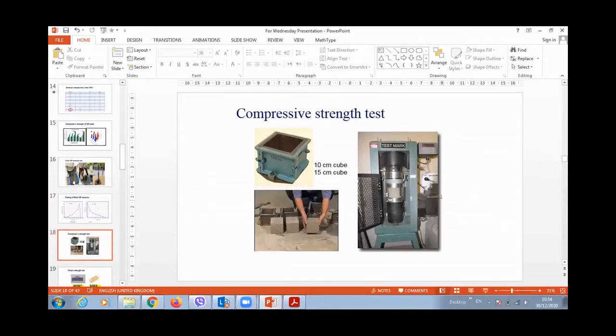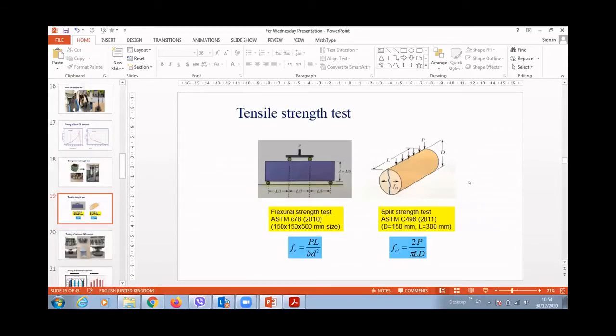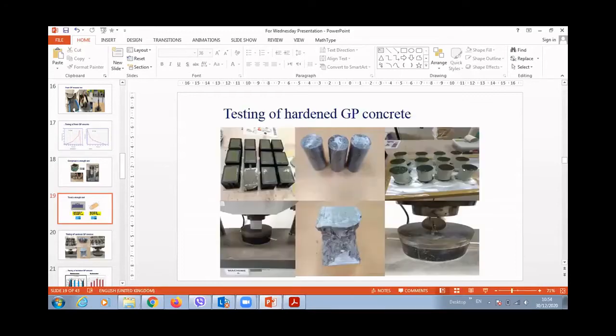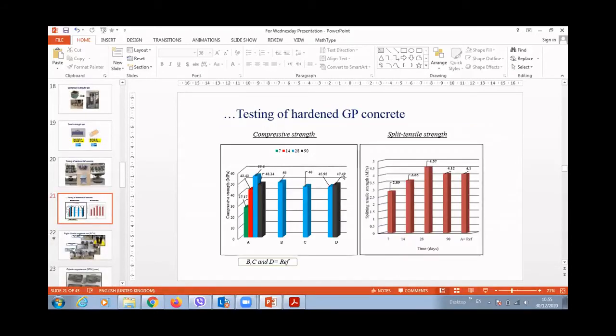So these pictures just show the regulation we follow to test the compressive strength. It's a cube of 10 centimeters, 15 centimeters, following the ASTM standards. And also here for the splitting, we use the cylinders and we calculate the splitting tensile for the concrete. And the casted samples, as you can see here, are both cubes and cylinders, and the test carried on. And this one is the result for the compressive strength and splitting strength for the concrete made based on the main formulation we found for the geopolymer paste previously.